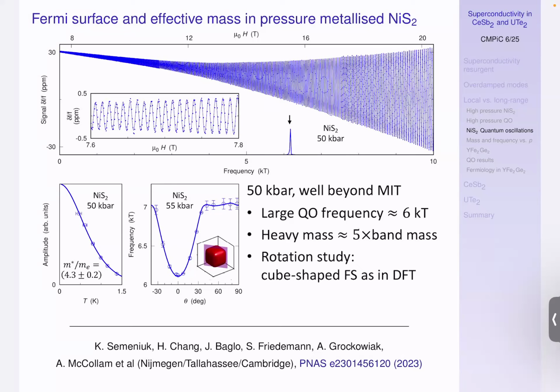Now you might say, why does band structure calculation give me metal at all? Because this is an insulator. But the point is, it's only an insulator because of strong interactions, and they're not apparent in the band structure calculation. So band structure calculation actually gives me the metallic state, which I need pressure to induce.